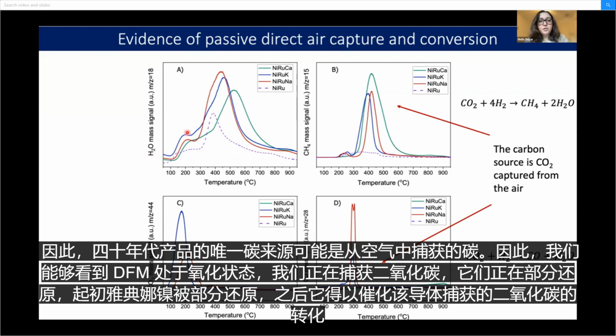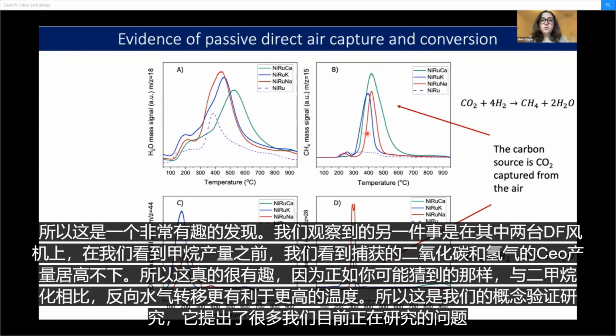They were becoming partially reduced initially. The nickel ruthenium was getting partially reduced, after which it was able to catalyze the conversion of this direct air captured CO2. So this was a really interesting finding. And another thing that we observed was on 2 of these DFMs, we saw CO production from captured CO2 and hydrogen before we saw methane production.